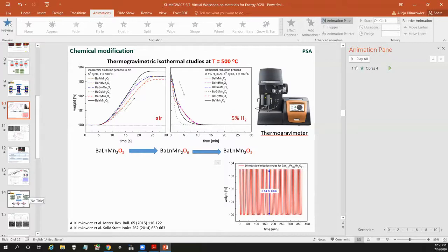Particularly in the case of the oxygen vacancy mechanism, an intake of oxygen causes a decrease in the vacancies. That usually makes the diffusion of the oxygen ions via oxygen vacancies slower. So why is the oxidation so fast in this case?